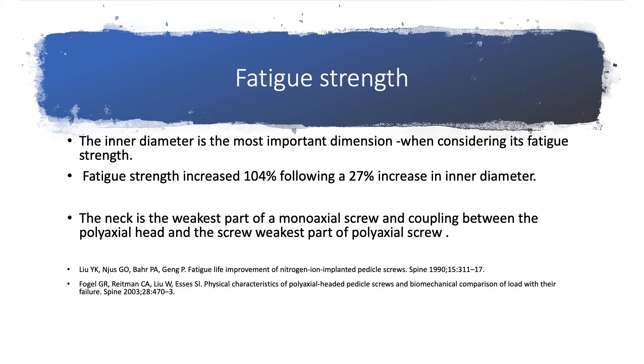Now let's see what affects the fatigue strength of a pedicle screw-based system. Whereas pull-out strength depends on the outer diameter, it is the inner diameter that is the most important dimension when considering fatigue strength. Biomechanical studies show that fatigue strength increases almost 100% following just a 27% increase in inner diameter. The neck is the weakest part of a mono-axial screw, and the coupling between the poly-axial head and the screw itself is the weakest part of a poly-axial screw.